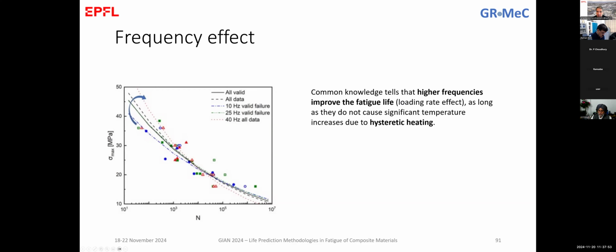What was the problem that tells not to use this 40 hertz for the specimens is that by using 40 hertz, we increase a lot the tab failures. And this again is because of the loading rate that is very high. So the tab failures are becoming much more frequent in this sense.